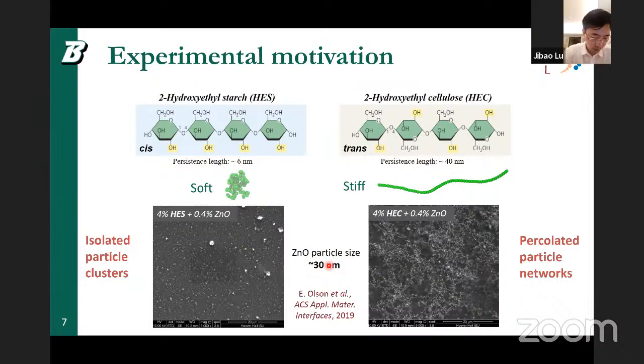Okay. So what's the ratio of the persistence length of the polymer with respect to the particle's diameter? This varies. For one polymer, it's small, less than the particle diameter, and for HEC, in our simulation it's much longer than the particle diameter, but in the experiments, as you see here, it's about 1.3.